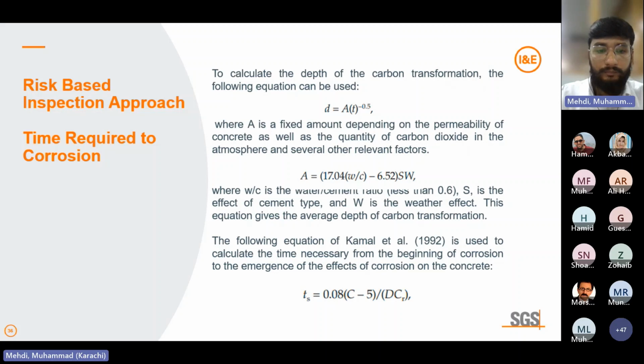So similarly, in the second equation, we have the water cement ratio, W upon C, S is the effect of the cement type, and capital W is the weather effect. This equation gives the average depth of the carbonation, and therefore, when calculating the maximum depth of the carbonation, one should increase the value by 5 to 10 mm, and S can be taken as 1.2.